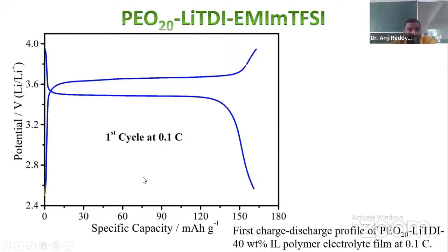And this is the battery testing. I studied only the first charge discharge cycle for LiTDI and ionic liquid, 40% of ionic liquid. See, here also we have achieved more than 160, around 163 or 164. This is the specific capacity we achieved at room temperature. Whatever cyclic performance we are observing here is at room temperature and with LiTDI salt. After adding 40% ionic liquid, we achieve a specific capacity of more than 160. That is a good value for practical use.